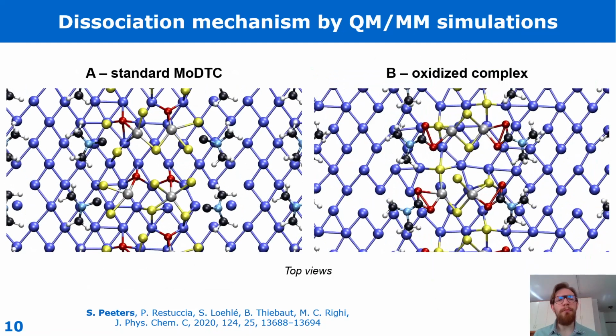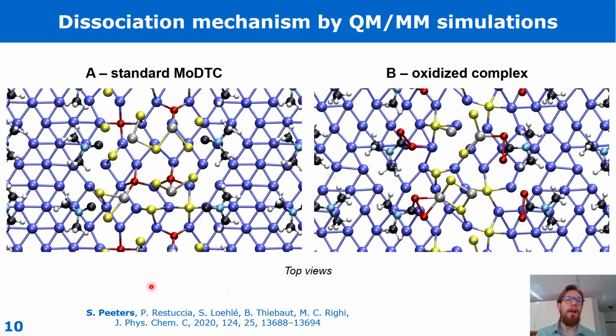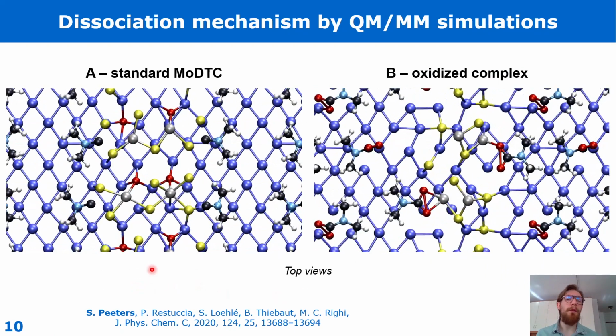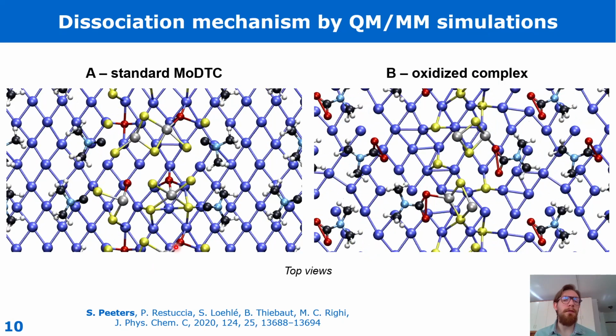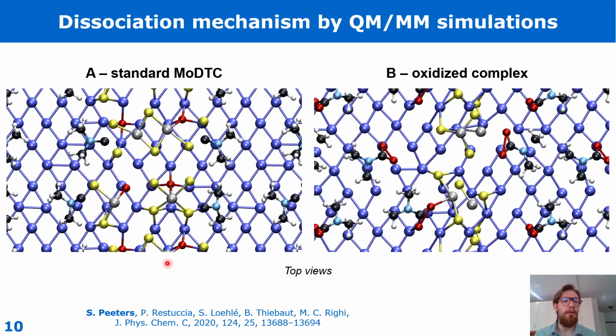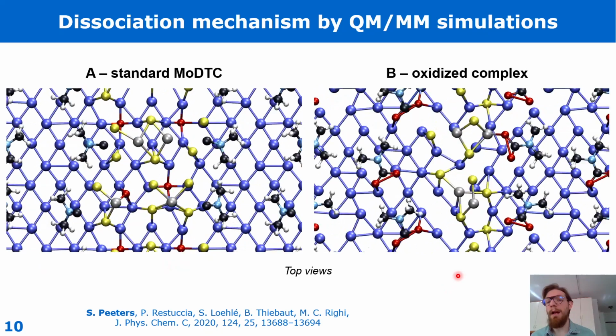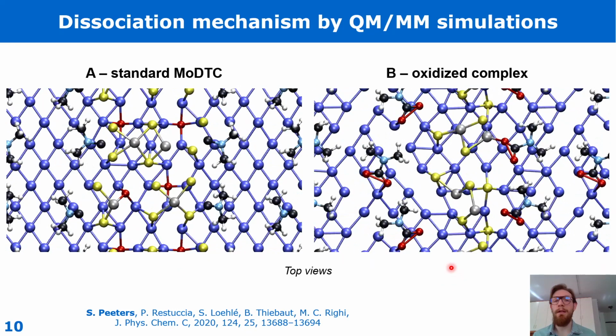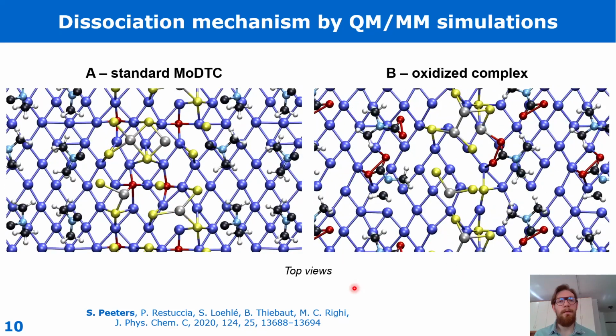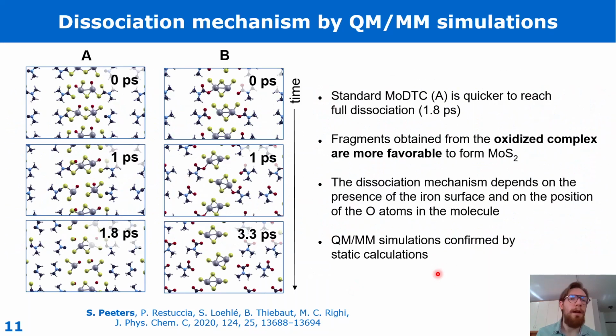So in these two movies, you can see two different simulations. On the left, we have a MoDTC molecule with the oxygen atoms in the standard position, which is the middle, the terminal position. On the right, you have an oxidized MoDTC complex with the oxygen atoms in the ligand position. As you can see, there are some differences in the reactivity that can be well visualized by looking at these snapshots. Here on the top, you can see the initial conditions. In the middle, the systems after 1 picosecond, and on the bottom, the two systems at the end of the full dissociation, which happens at two different times for the two molecules.